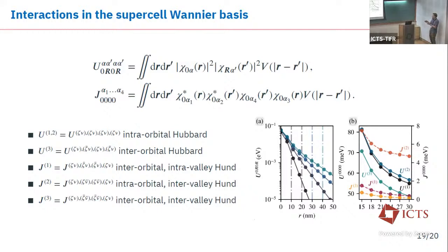So we have an ab initio motivated model for all the interactions, all the repulsions for electrons in that system. And the very important point is that all of this places the model firmly in the weak coupling regime. For a supercell size of 24 by 24 primitive cells in a single supercell, which is roughly around 6-7 nanometers in size, we have a ratio of interactions over bandwidth of roughly 0.15. So that makes it perfectly suited to weak coupling studies of that model.